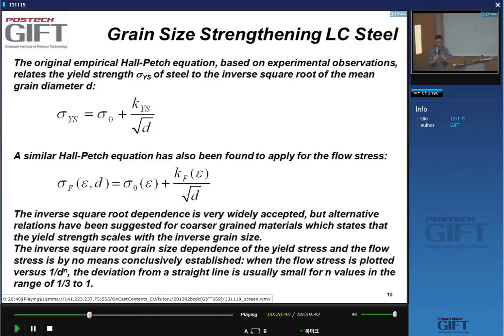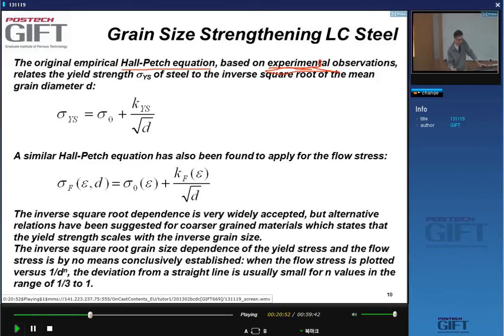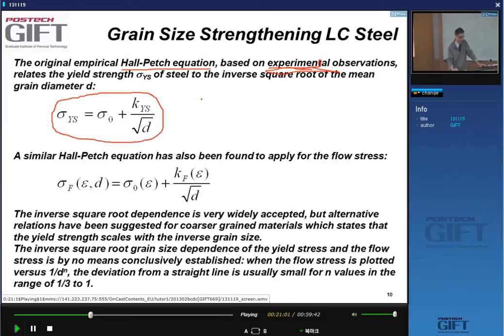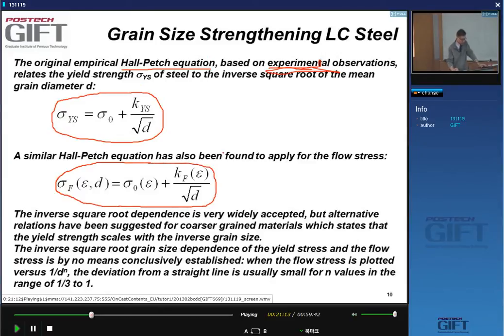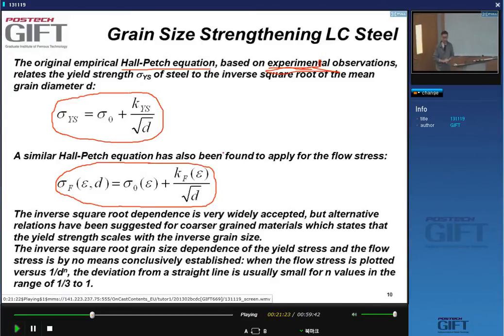Let's now have a closer look at the Hall-Petch equation. The original equation is based on experimental observation — people checked it and it looked like a straight line. It was originally designed for the yield strength of steels. Later it was noticed there was also a Hall-Petch-like equation for flow stress — any amount of strain was also somehow related to one over the square root of the grain size.